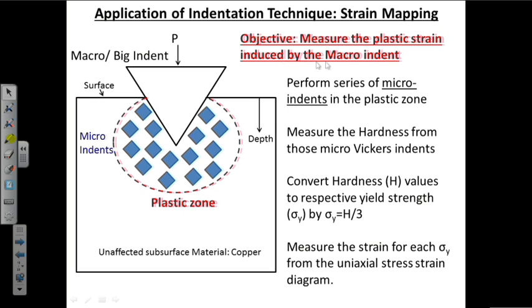Now, to measure the plastic strain induced by this macro indent, what we need to do? We need to calculate or measure the strain at each point inside the plastic zone, and for that we perform a series of micro indents inside the plastic zone. Once we perform the series of micro indents, we can measure the hardness values from those micro Vickers indents. And then we can convert those hardness values to their respective yield strength by using sigma y equals H over 3. This relationship was discussed in the first lecture. So, we use this relationship to estimate the yield strength at each material point where those indents were made. Now, if we know sigma y at each point inside the plastic zone, we can measure the strain corresponding to each sigma y from the uniaxial stress strain diagram.